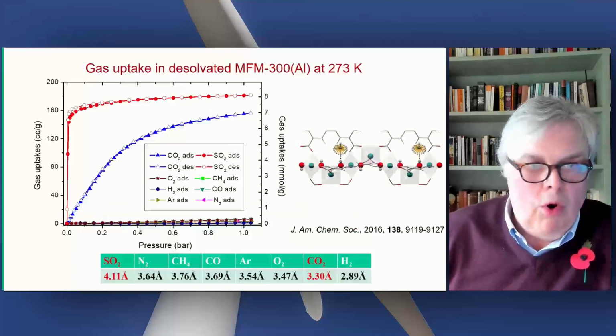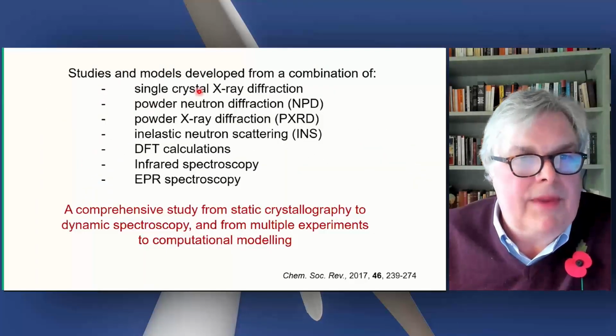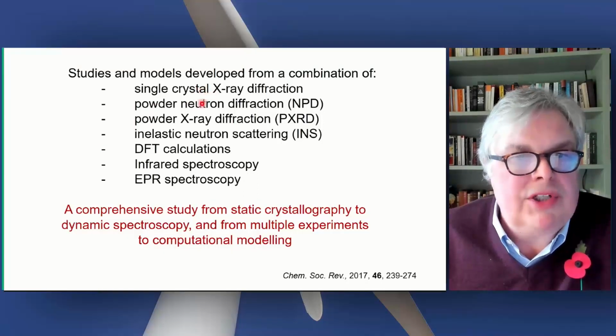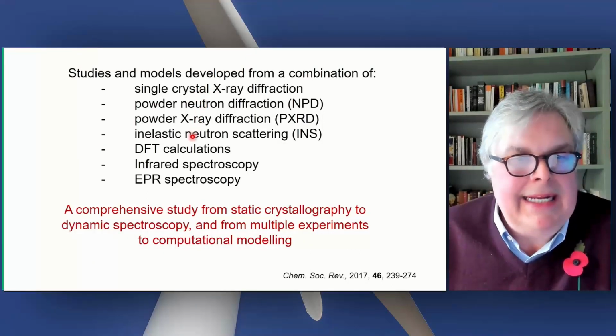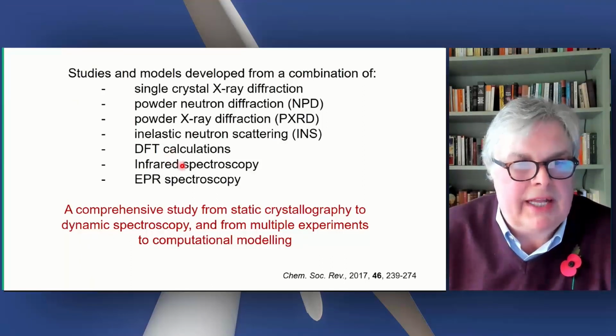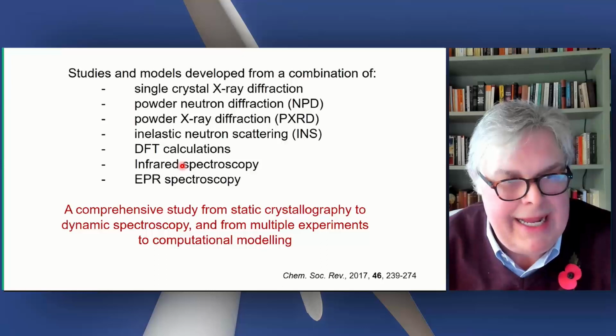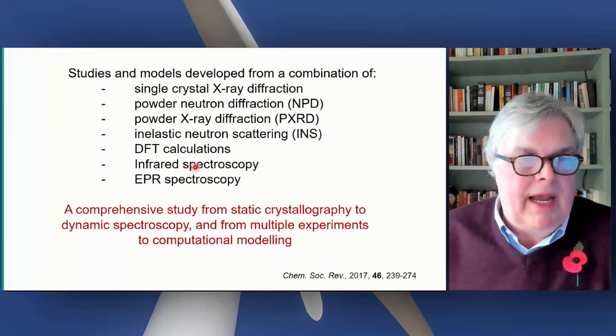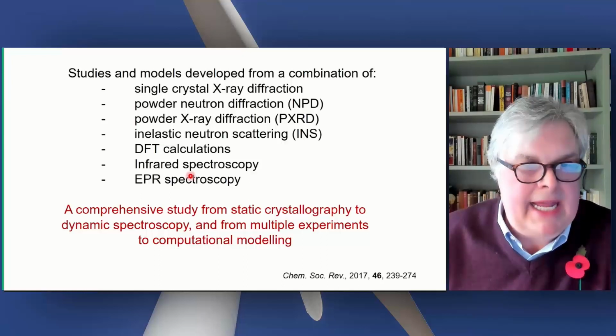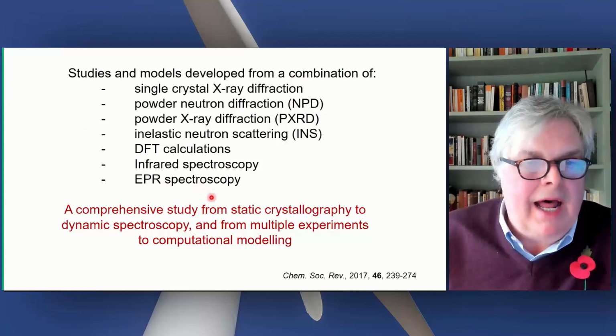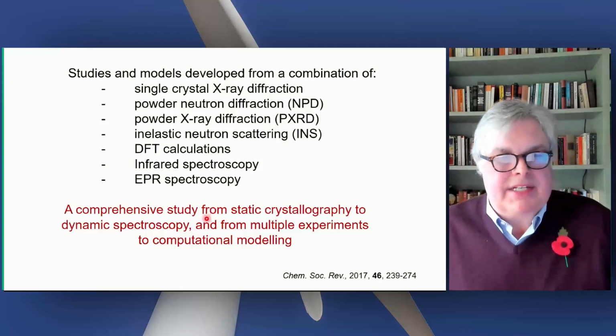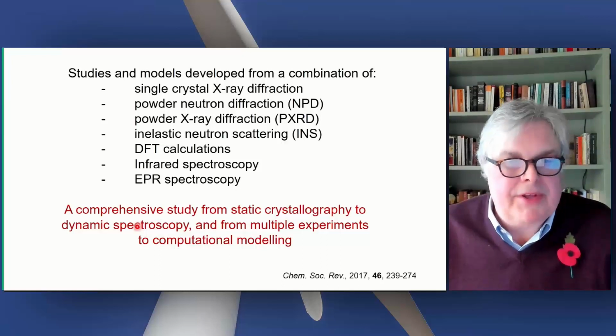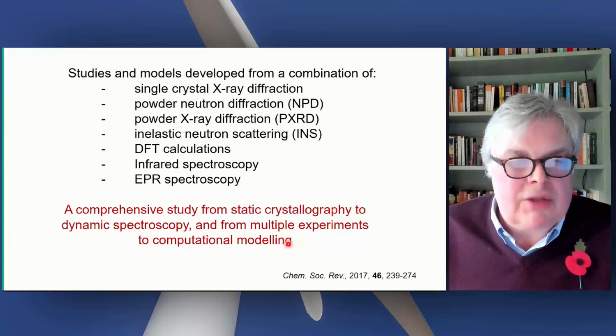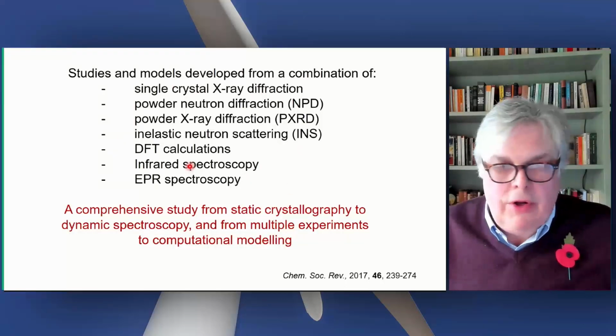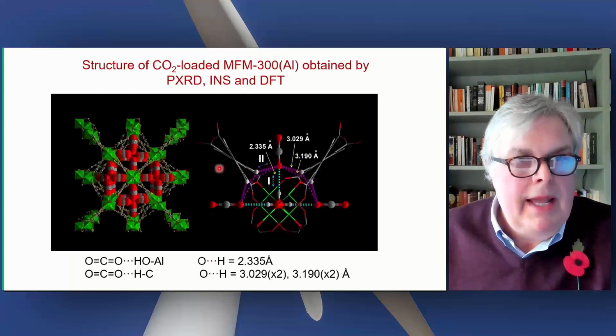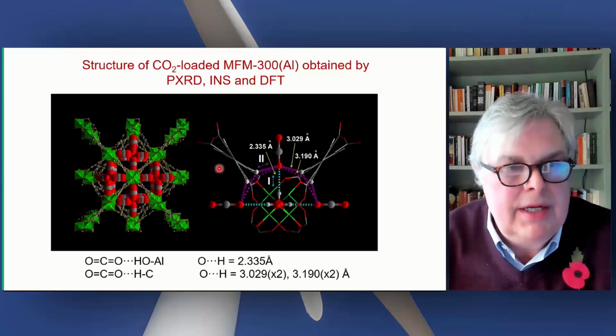Okay, so what we have now done is combined single crystal X-ray diffraction, powder neutron, powder X-ray, inelastic neutron scattering, DFT calculations, and also synchrotron in situ infrared spectroscopy and also EPR spectroscopy linked to ENDOR to really analyze and give a comprehensive analysis using static and dynamic methods plus computational modeling to really understand what is going on with these MOF materials. Here is a powder X-ray diffraction structure.